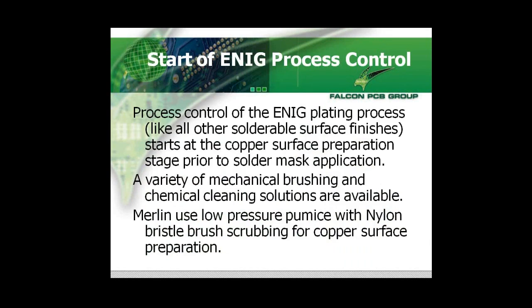Initially, the process control of the ENIG process, like all other solderable surface finishes, starts at the copper preparation. This is after outer layer strip etch strip and prior to solder mask application. There are a mixture of mechanical brushing or chemical cleaning solutions available. At Merlin, we tend to use a low pressure pumice with nylon bristle brush scrubbing for the copper surface preparation. We have used this for many years and it's proved very, very successful.